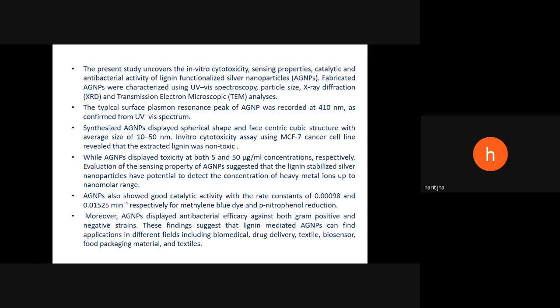They also show good catalytic activity with a rate constant of 0.00098 and 0.01525 for methylene blue dye decolorization and for paranitrophenol reduction. Moreover, the silver nanoparticle displayed antibacterial efficacy against both gram-positive and negative strains. These findings suggest that lignin-mediated AgNP can find application in different fields, including biomedical, drug delivery, textile, biosensor, food packaging material, and textile. Okay, so these are some of the areas in which it can be used.